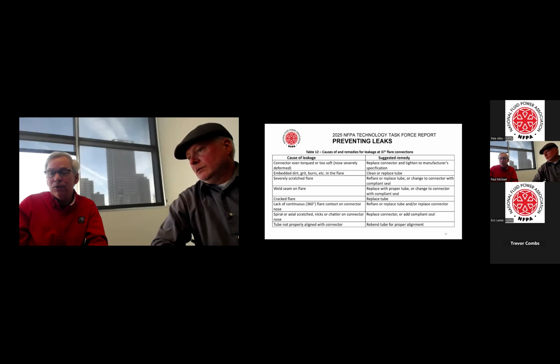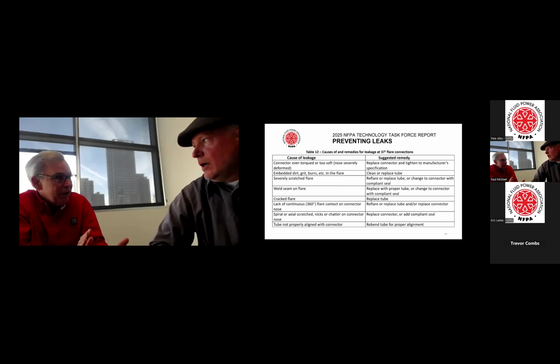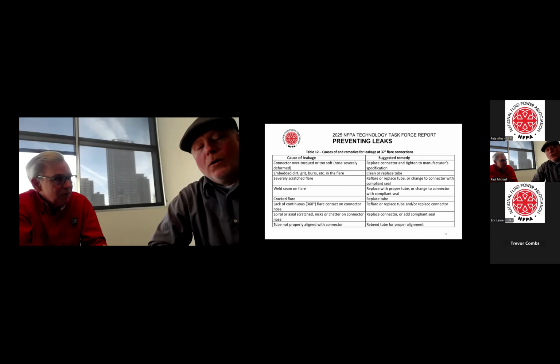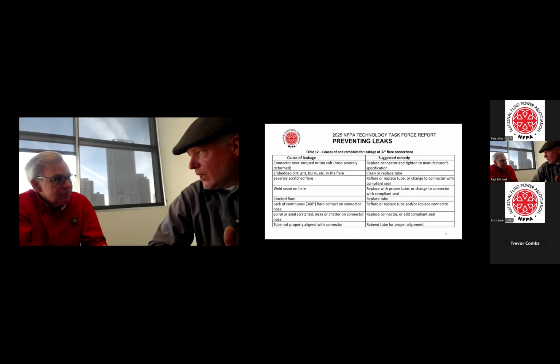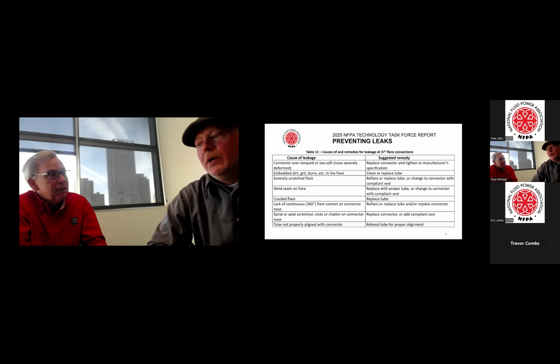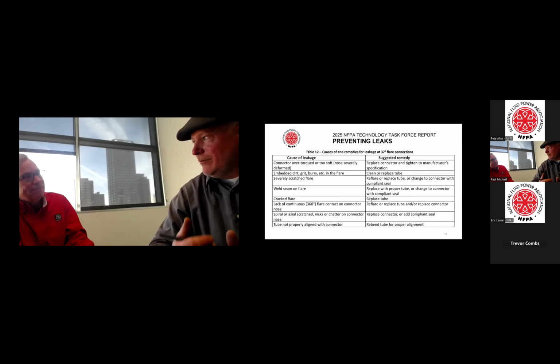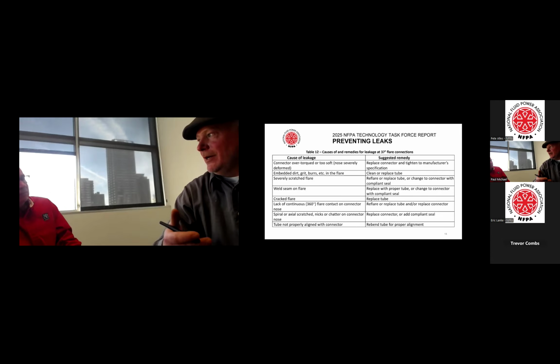So the cracked flare is where you're talking about a significant problem, and you just got to replace the whole tube. Or you cut it back, depending on how the tube run is done. Sometimes you can cut it back and reflare it. But again, that crack usually starts out as a drip, and then somebody goes to tighten it and they make the drip a little worse. And then they crank on it even harder. Now they've damaged the fitting, and even further trying to repair, because even if you do reflare, you're still going to have a damaged fitting. So now you have to replace your fitting and your tube because you didn't identify the leak correctly.